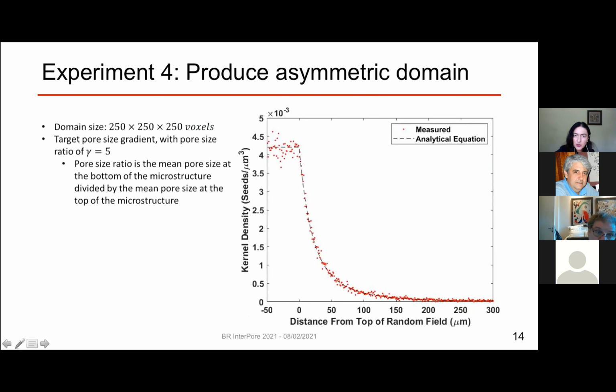It's seeds per micrometer cubed. And on this axis, on the horizontal axis, we see the distance from the top to the bottom of the random field. And we see that the density is much higher at the top of the random field, and then it just decreases towards the bottom. And this is how we can control the pore size of the void space throughout the entire domain.